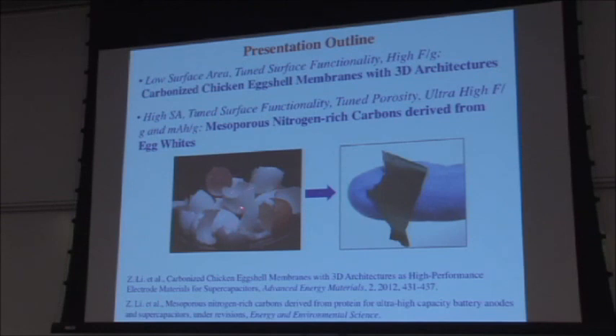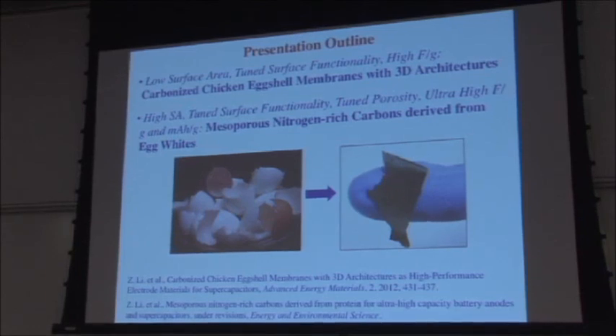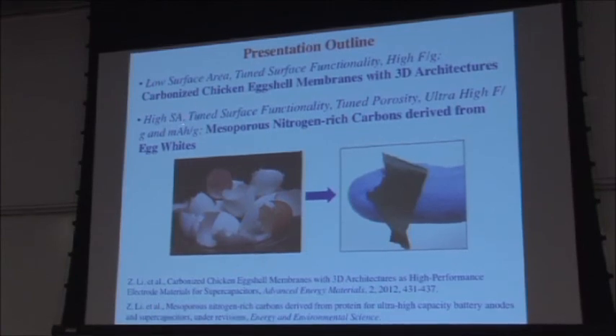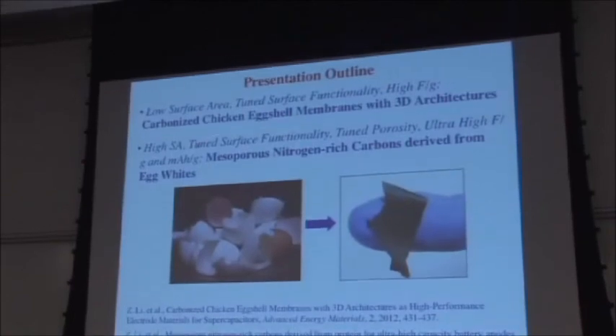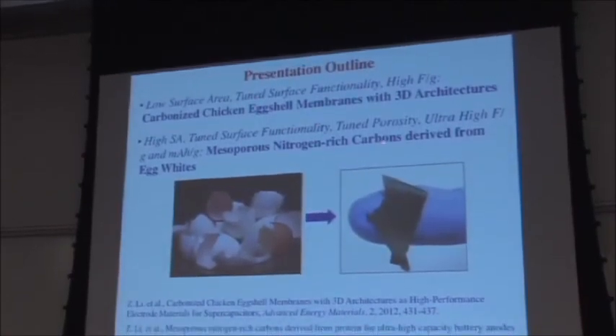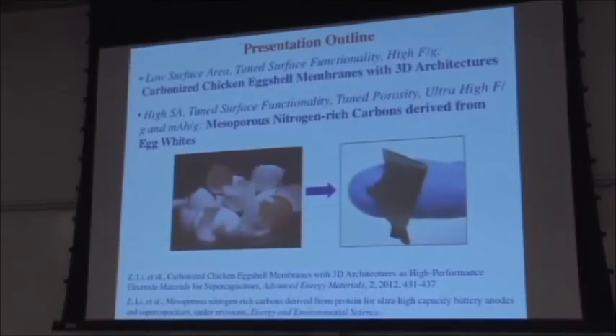So here you have a bunch of chicken eggshells. And after you carbonize it, it looks like this quite thin construction paper that's flexible. You could actually stack it. You could carbonize it to be thicker. And it's a very easy geometry to work with as far as supercapacitor electrodes go. Because again, if you want to put this in a flexible device, it's quite easy. The next stuff, which we're quite excited about, is a fairly high surface area material with tuned surface functionality and now tuned porosity, and actually ultra high farads per gram.